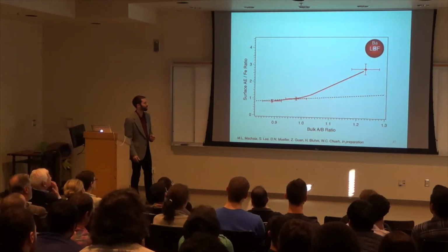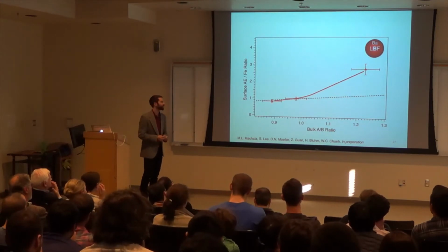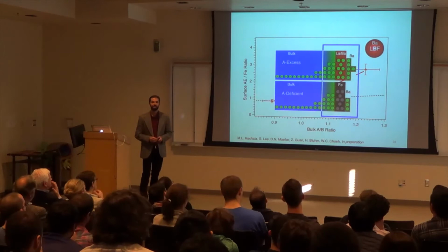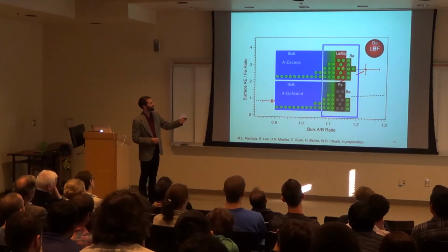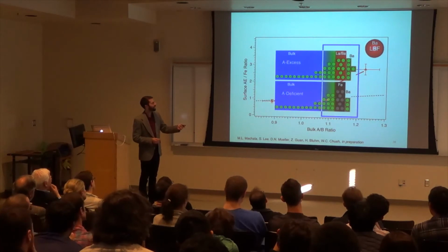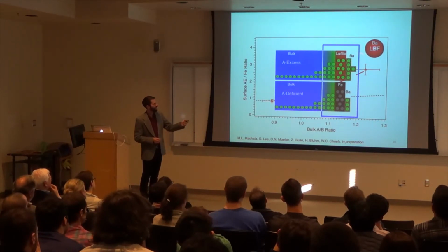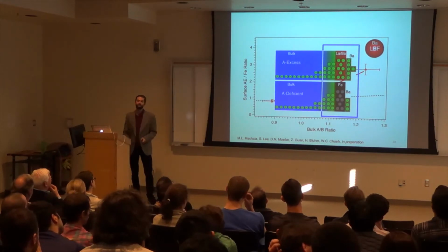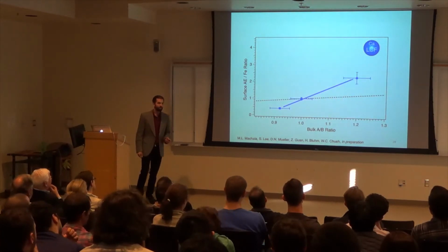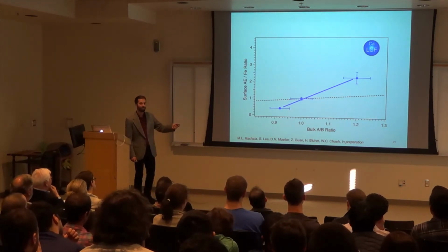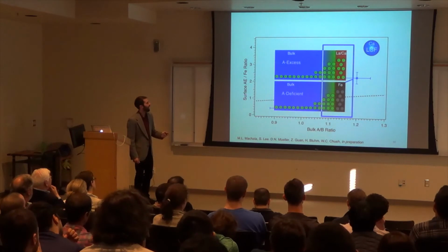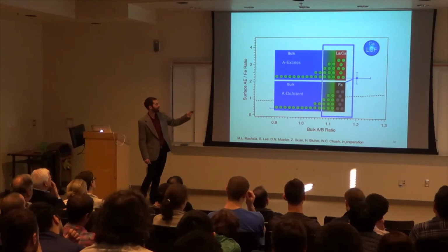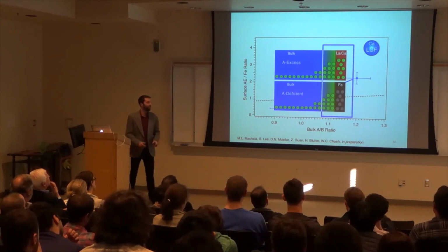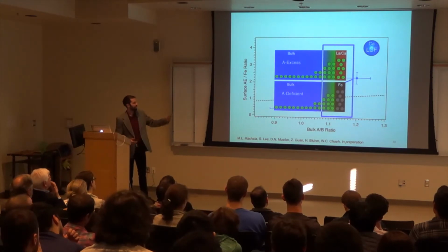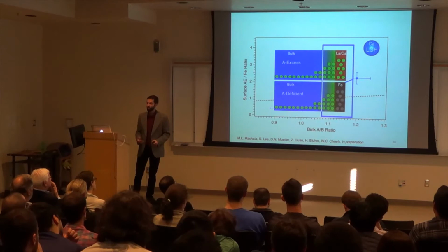So for the barium-containing sample, remember this is the one with the biggest ionic radius mismatch, we see a similar trend. We see that there's an A-side enrichment in the A-side excess, and we see a B-side termination on the A-side deficient sample. And just like we saw with the side peak, we have an accumulation of just barium atoms on the surface. With the calcium, we actually see a similar trend too. You can see that it doesn't fall on this line. The surface does change. There we actually see segregation, and we also see the same trend that we saw previously: for A site excess, we see a termination of A site cations. For the A site deficient, we see a termination of the B site cations, including the iron.